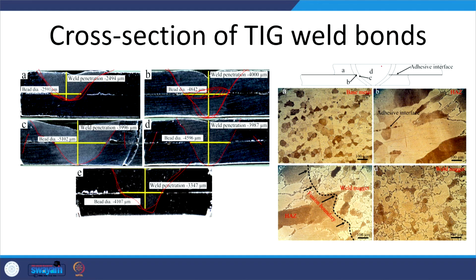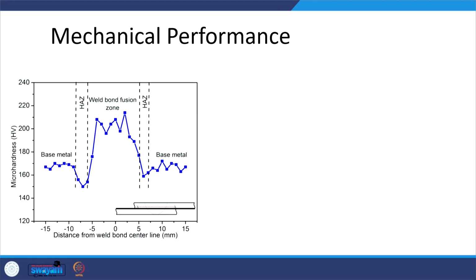The fusion zone, because of the rapid cooling, results in a fine grain structure, while the heat affected zone produces a coarse grain structure because of grain coarsening, and this is how we can see the fusion boundary, the weld nugget and the heat affected zone, and this is the base metal. So, if we compare, because of the excessive heat generation, the base metal is coarsened as a heat affected zone, and the weld metal is refined because of the rapid cooling, and this is the weld interface. Since in this case steel was welded, certainly some kind of hardened phases will be formed. So, as compared to the base metal in the heat affected zone, the weld zone is harder and stronger.